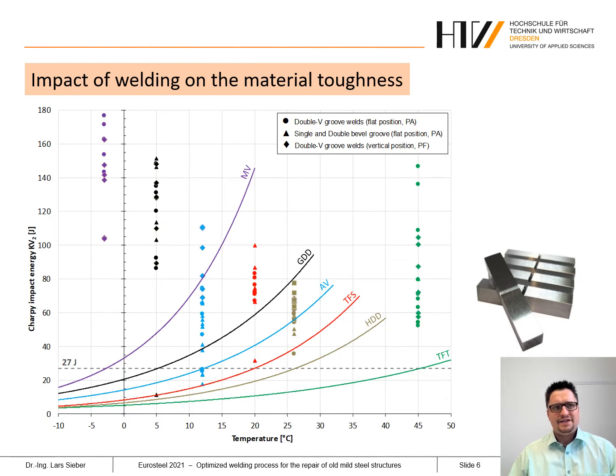To evaluate the ductility of the welded joints, the toughness was analyzed in Charpy impact tests. The toughness of the unaffected base material was determined first as a reference value. Based on our experience, the transition temperature in Charpy impact tests for old mild steels is approximately in the range between 0 or a little bit below and plus 40 degrees Celsius, similar to these 6 materials here.